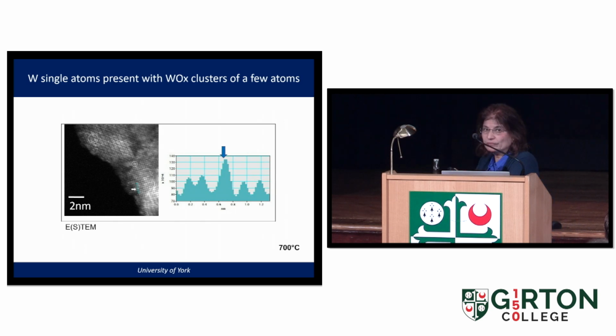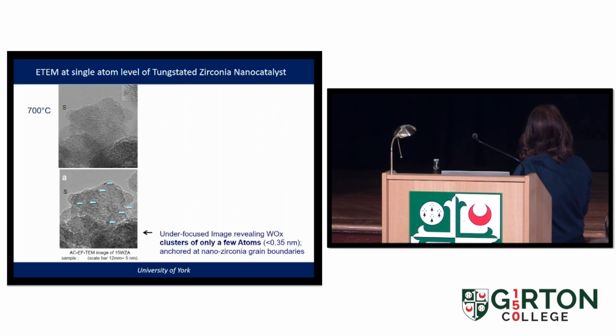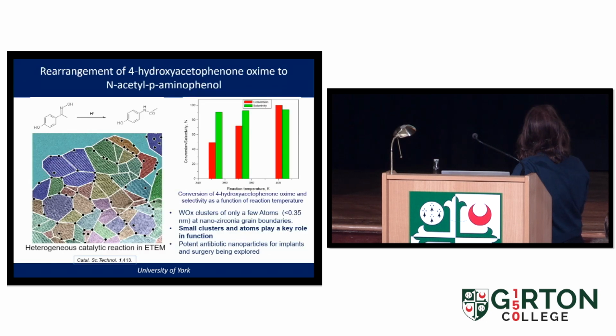Zirconium, as many of you know, is used for jewelry, but zirconia, when it's oxidized, is a very stable ceramic support, and that's what we're using here. If you look at it very carefully, we have anchored all these atoms and clusters along the grain boundaries of zirconia. I can show you in a colorized image. All these tungsten atoms and clusters are anchored very nicely, so they don't move around and sinter.